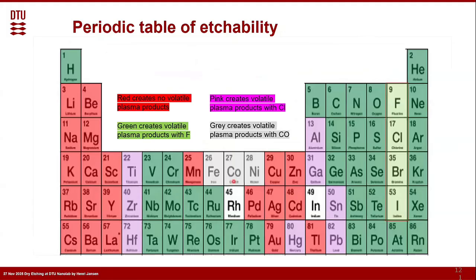Now, what we do is, okay, let's check all the numbers, using Trouton's law or the Antoine parameters. If we have that available, that's even better. And with the boiling temperature and Trouton's law, we just say in the periodic table what happens. And we say that everything below 300 degrees will get a color depending on if it etches with fluorine, it's getting green. So everything you see over here in green is etchable when you use fluorine radicals. The pink is for chemicals we are using chlorine plasmas. And here you see some gray ones, and they are etchable with carbon monoxide plasmas.